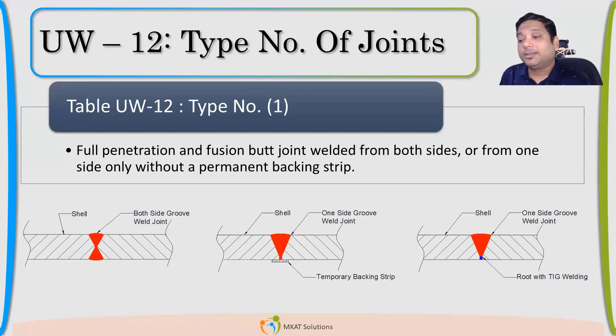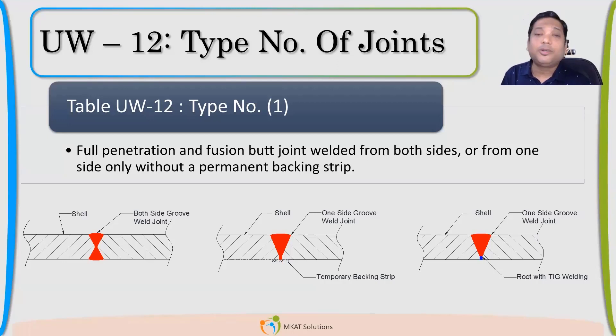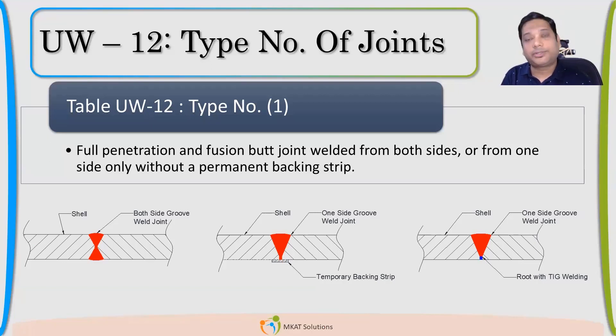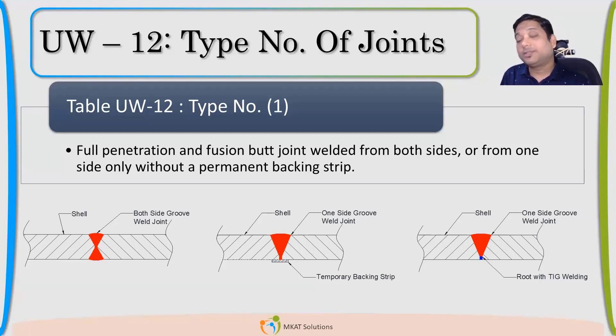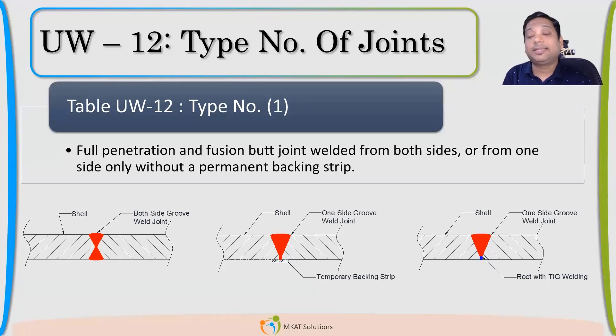What they do is fuse the root with TIG. By using TIG, they first fuse the root and then do the welding. By using this technique you can achieve full penetration, but that will not guarantee it — you have to demonstrate it, as that is the complete capability of the fabricator. You have to do mock-ups and train your welders. Once the mock-up is qualified, it will be tested to verify the roots are completely fused.